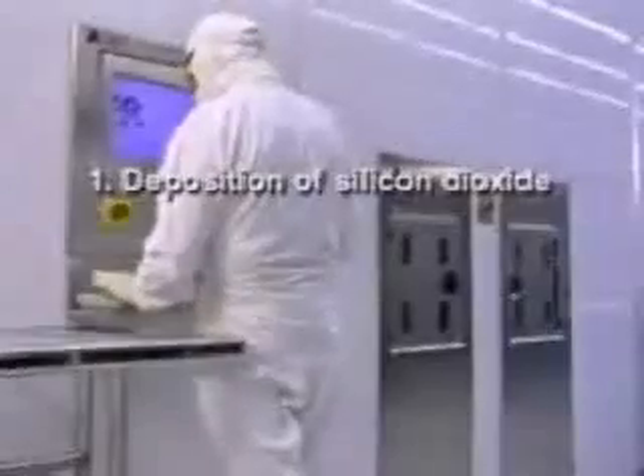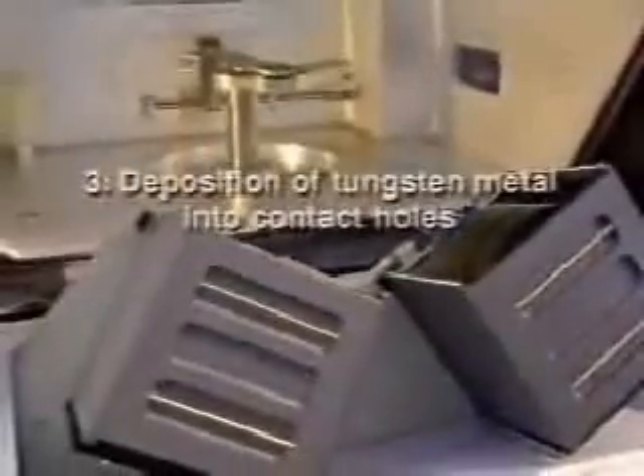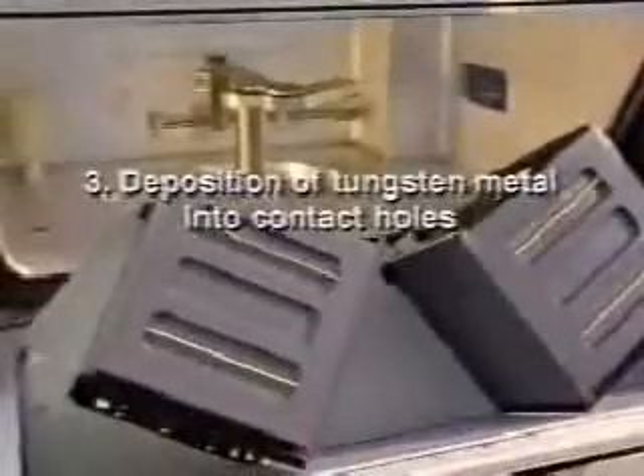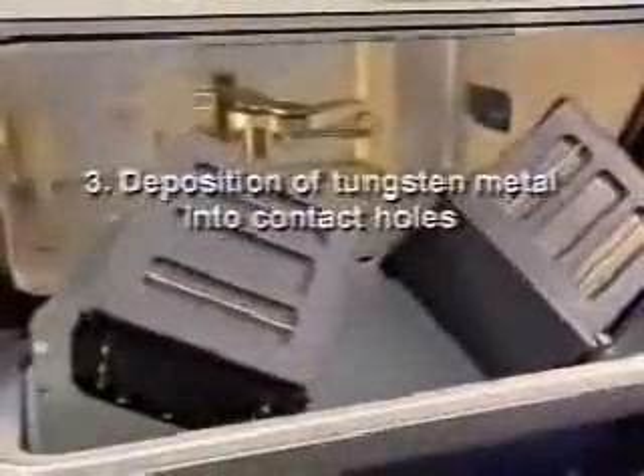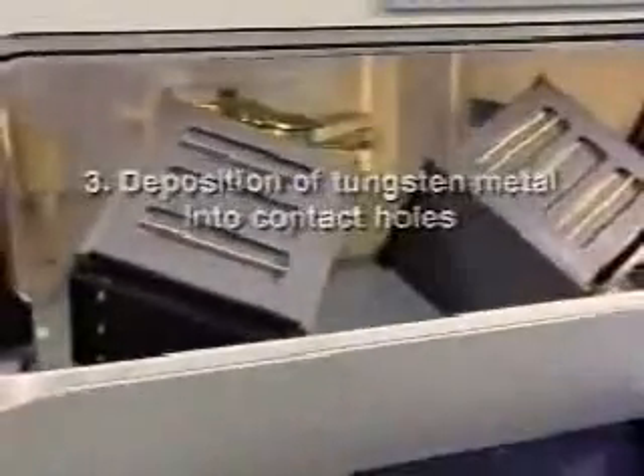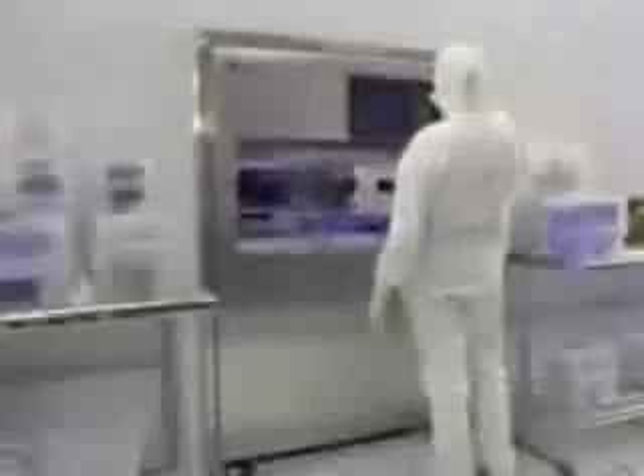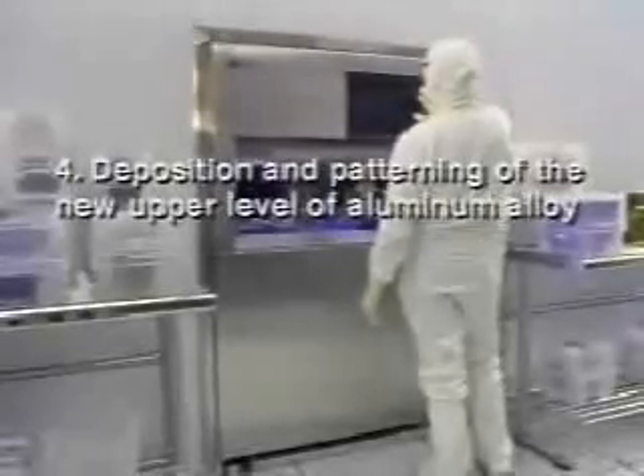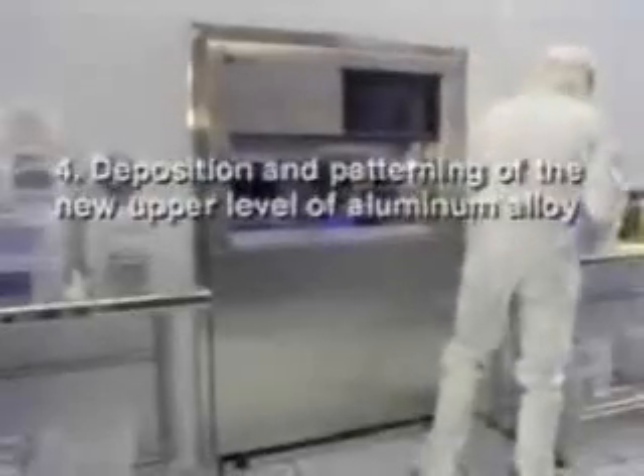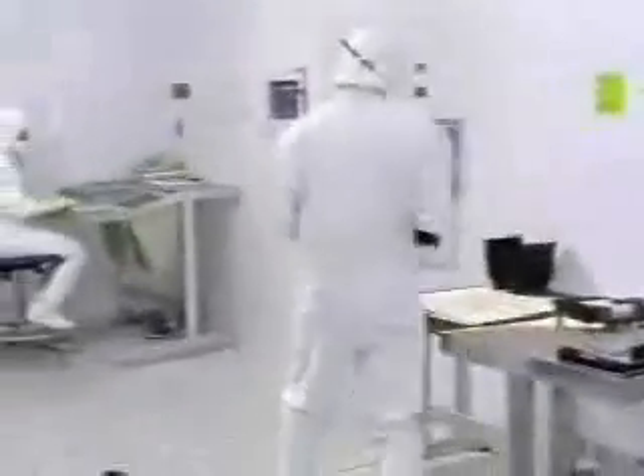Deposition of silicon dioxide to electrically insulate one layer of wiring from the subsequent levels. Photolithography, masking, and etching to open contact holes between the top layer of metal and the next layer to be deposited. Deposition into the contact holes of another tungsten plug. This ensures a good electrical connection between wiring levels and a more planar surface. Deposition and patterning of the new upper level of aluminum alloy.